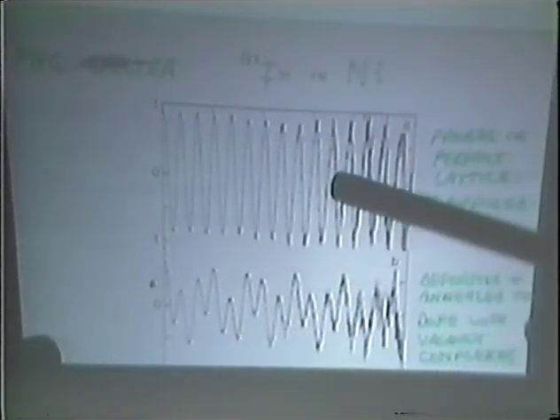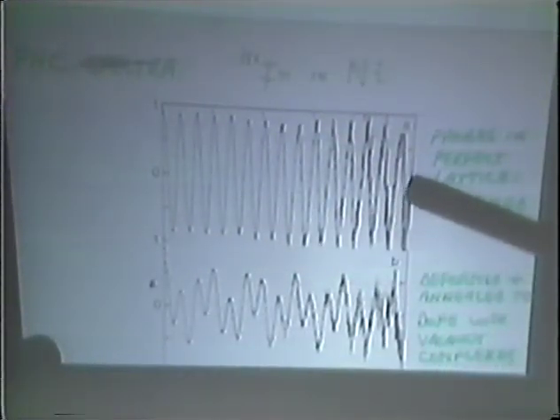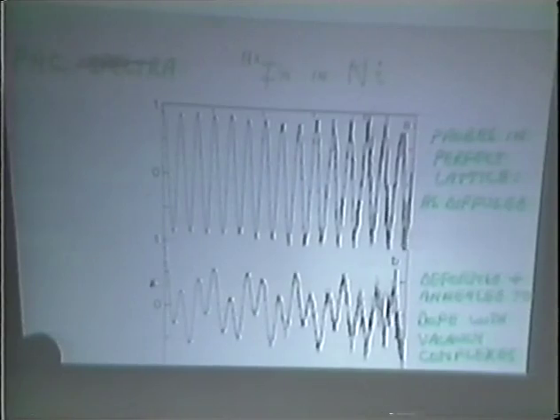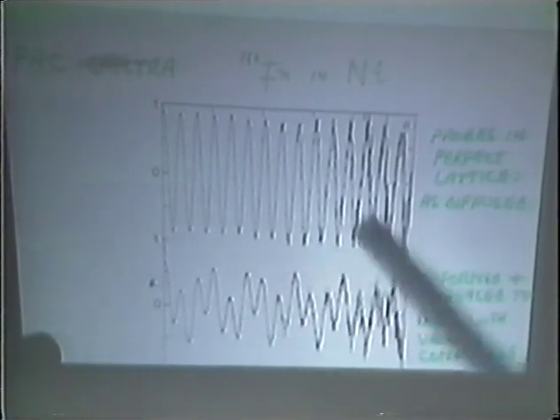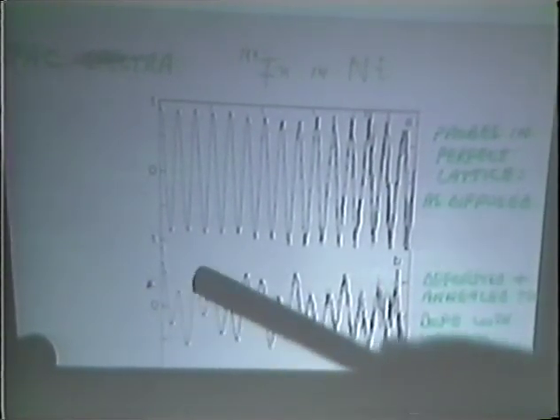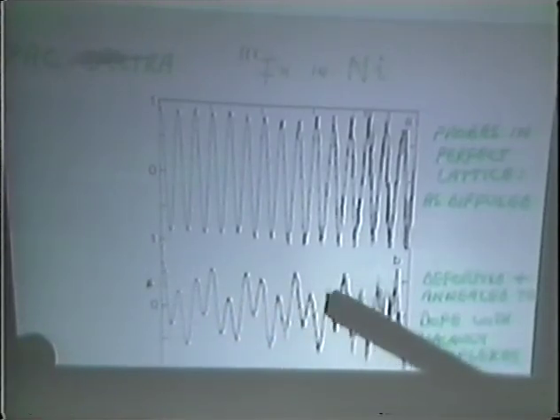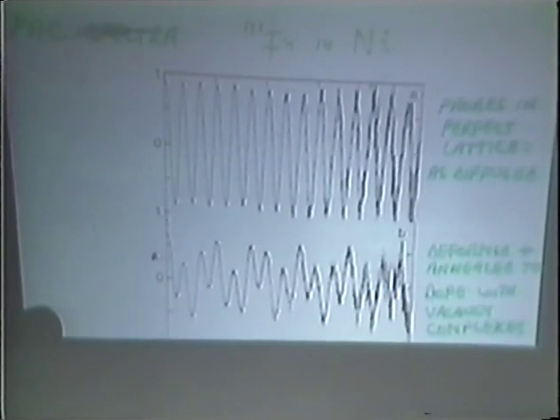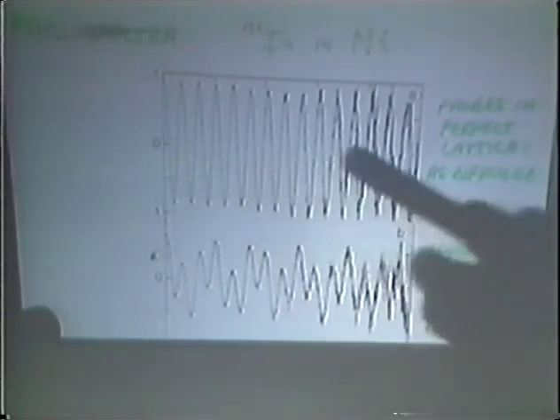Let me show you how that works, this defect trapping in nickel. If you take a piece of nickel, diffuse the indium into it, and then make a measurement, you'll find a very large amplitude, high frequency precessional signal due to indium on defect-free substitutional lattice sites. If you then damage the nickel by plastic deformation and then anneal it to a temperature of 400 K, you'll see a reduction in the high frequency signal and the appearance of a low frequency signal. That's caused by trapping of a lattice defect. If we warm this up higher, that defect will detrap and we get back to where we started.